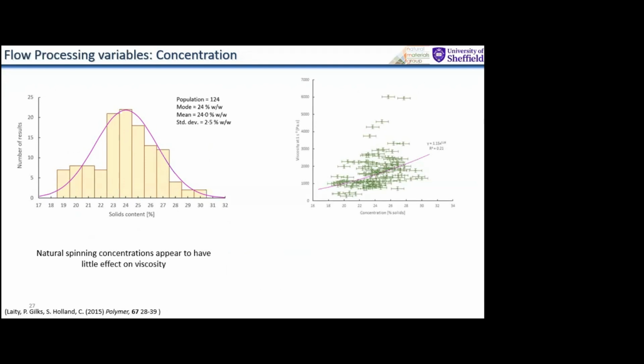We would expect concentration to the power 3.4, basically, to affect the viscosity of a standard polymer solution. We don't see that at all with silk. So silk basically seems to be a bit indifferent to changes in its concentration. Partly, I think, it's because it's a really long molecule that has lots of interactions with other ones around it. So it doesn't seem to have much of an effect on concentration.